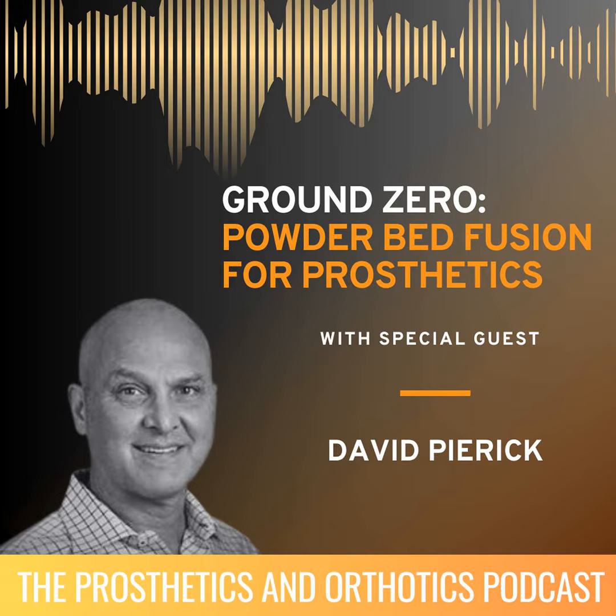Yeah, and I know at the time we were requesting feedback from the experts. Hey, what did we do right? What do we need to improve to make this better testing, more like real life? And it comes down to what is the peak strength of the component. So you do a short-term compression or tensile test, and then what happens if you're using this 1,000 times a day? And then cycling under the loads that you expect to see when someone's walking. And so that's what we did. We did both cycling as well as ultimate strength.